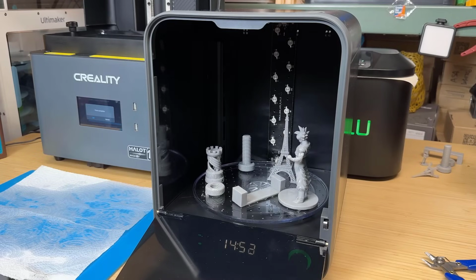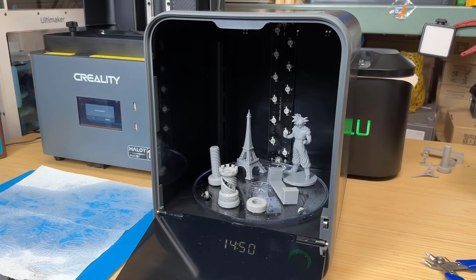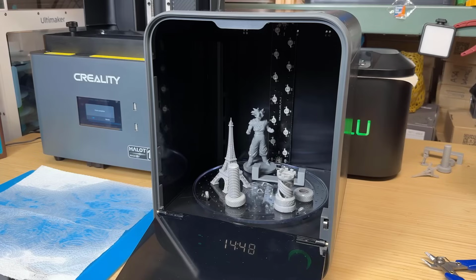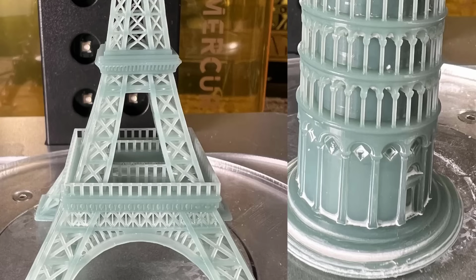For the dryer and UV box, I appreciate the drying feature. When using IPA, if the surface isn't completely dry before curing, you're likely to see some cloudy white spots on your model.